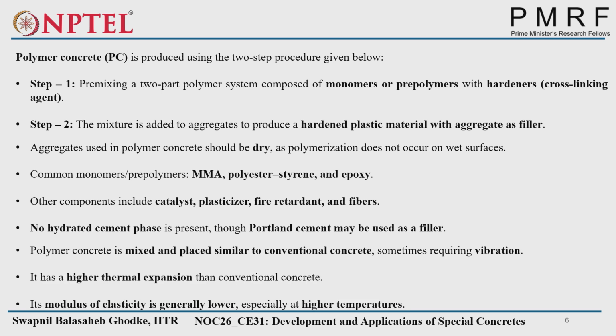Then the binder here will be only polymer, which will bind the aggregates. Cement may be there or may not be there. It depends on your composition of the concrete. But if cement is there, that will act as only filler because water is not present. Because if you want to initiate the cement CSH gel reaction, we require water as a reactant.